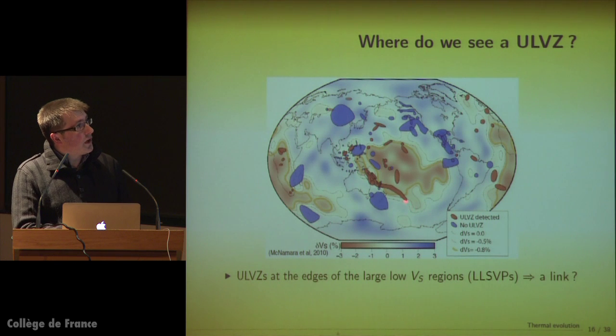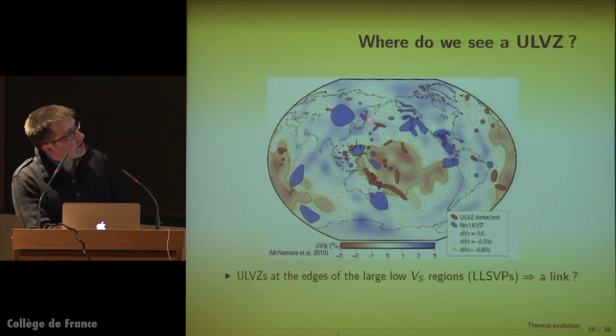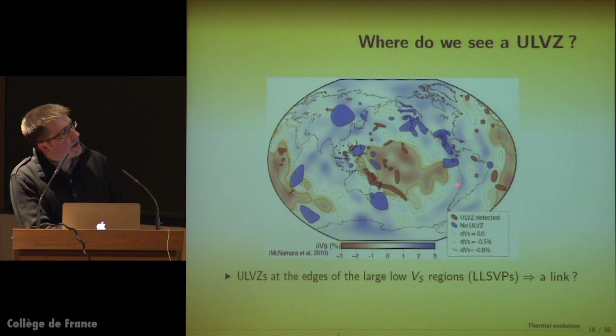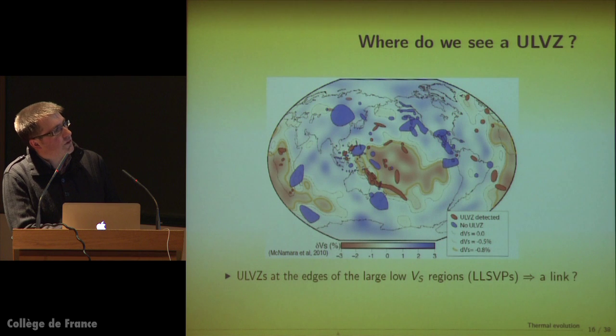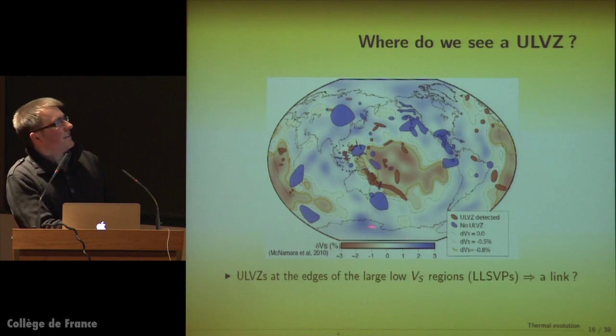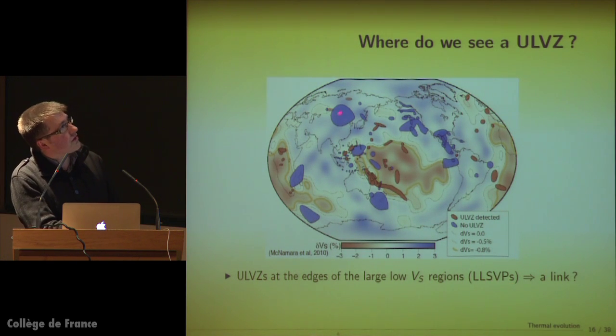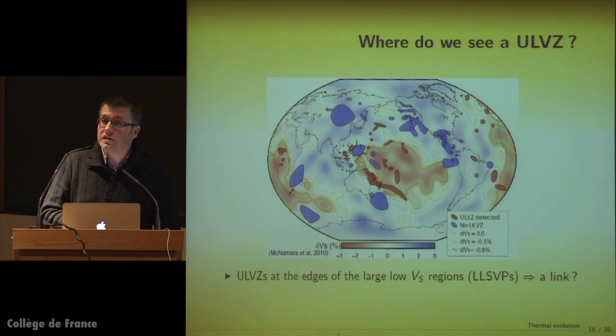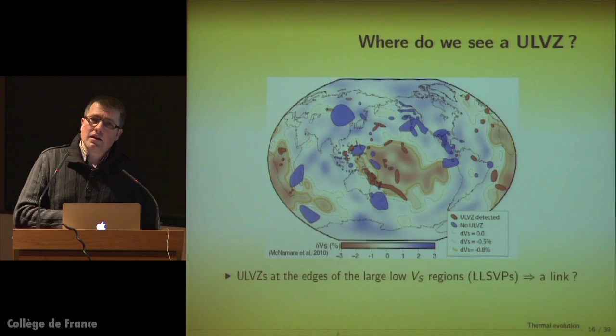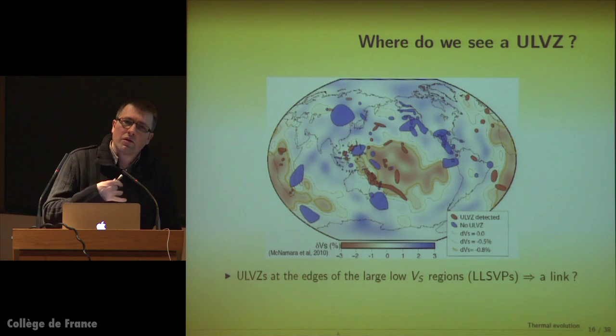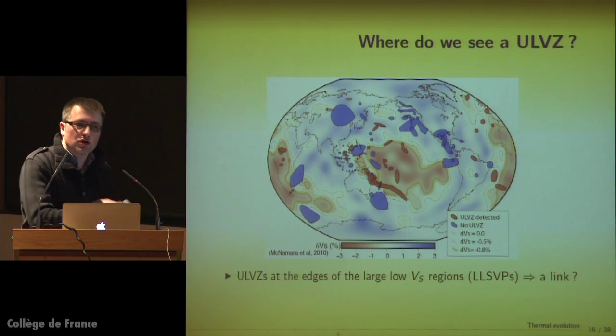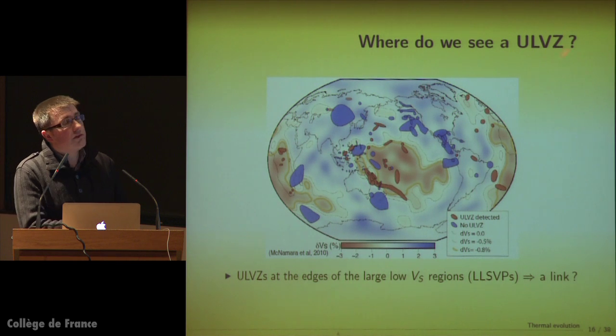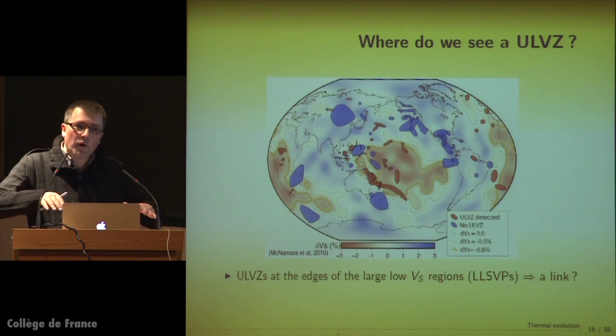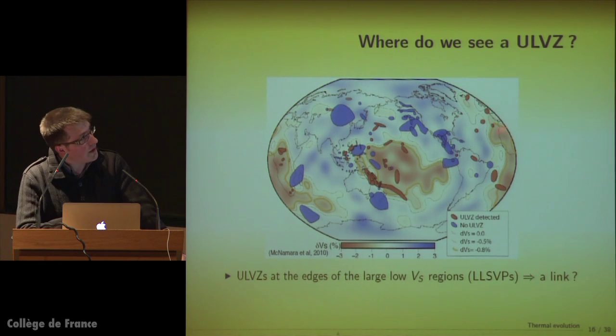We don't see them everywhere. I guess they are seen in these red regions. They correlate somehow with the edges of the large low shear wave velocity provinces, the LLSVPs. So that suggests a link. The blue regions here are regions where we don't see the ULVZs. So in fact, there are places where there are data, and these data don't show any sign of these ULVZs. So it's not a uniform feature. It's a patchy feature.